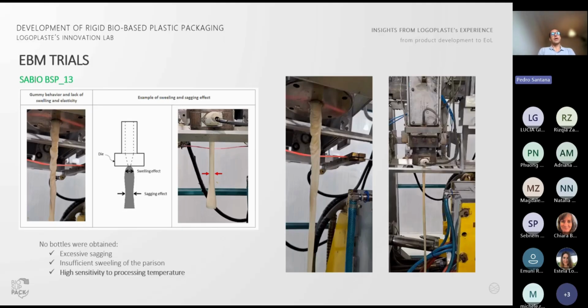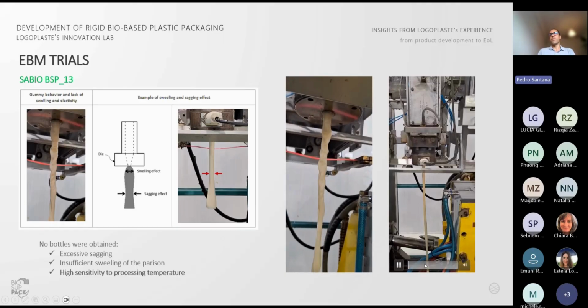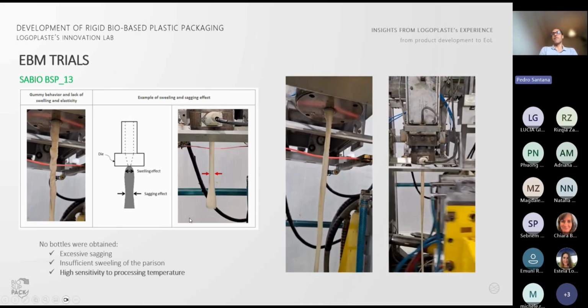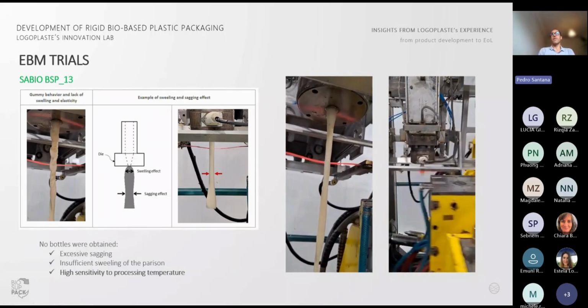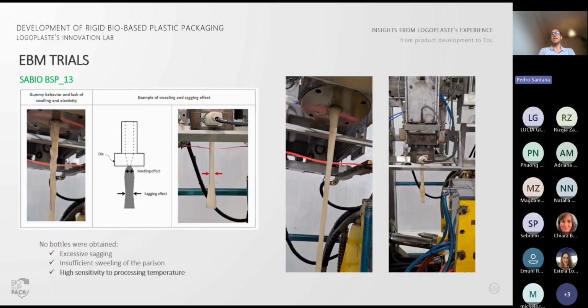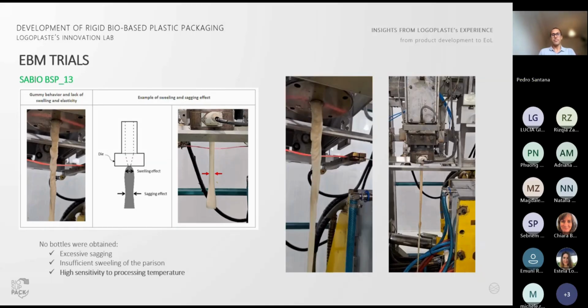We couldn't get bottles, and as you can see, the material behaved in a very strange way. It became very fluid or very degraded, and it didn't show any kind of swelling, and it showed very excessive sagging. It became very sensitive to the processing temperature, and that's the reason for this behavior.